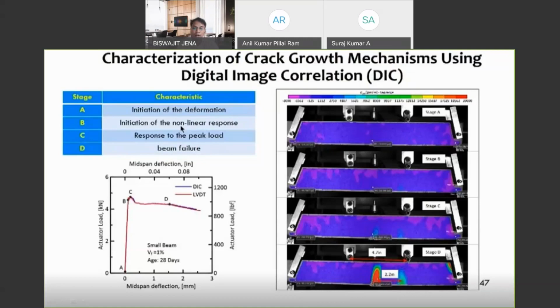When you come to stage C, which is at the peak, this is the fiber reinforced specimen. That is why you will see a lot of deflections happening here, and this is fiber reinforced mortar, not concrete. That is why you can see deflection happening. So at stage C, you will start to see some localization of strain in the tension zone of the beam. And if you go to stage D, which is further down in the post-peak region, you will see a lot of strains at the center point of the beam where you will likely have formed the crack.